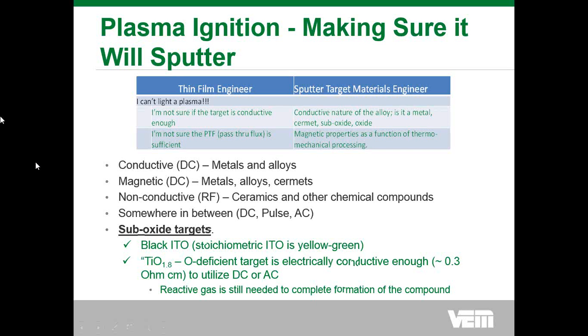I was involved in a previous life where we were supplying very, very pure nickel chrome alloys. But the phone rings and the customer says, my films aren't performing the way I want them to. In the table on the right there is a very good example of that, where you see a nickel chrome 40 as cast has a TCR, thermal coefficient of resistivity, of 93. As sputtered, that TCR is actually even a little bit larger at 112 ppm per degree centigrade. And even worse, with a high purity nickel chrome, you see that number jumps as high as 150.